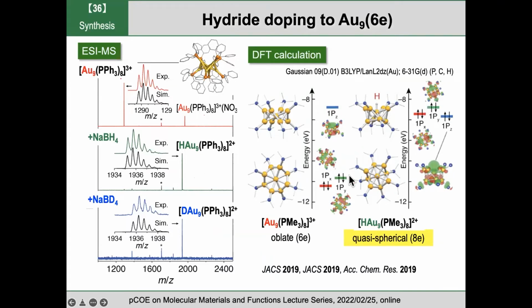According to theoretical calculation, before the H- addition, the p orbitals are split into 2 groups. One of the p orbitals along this direction is unstable, upshifted in energy. Okay, so 6 electrons is a good number, but after addition of hydride H-, the p orbitals become degenerate, and the total number of electrons increases to 8. Interestingly, one of the p orbitals is exposed because there's no ligand along this direction. So we can expect this species might have nucleophilicity against metal organic compounds.